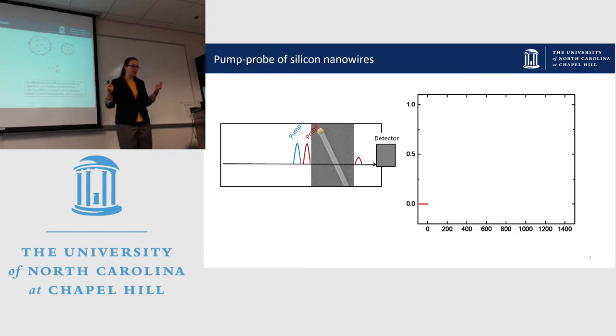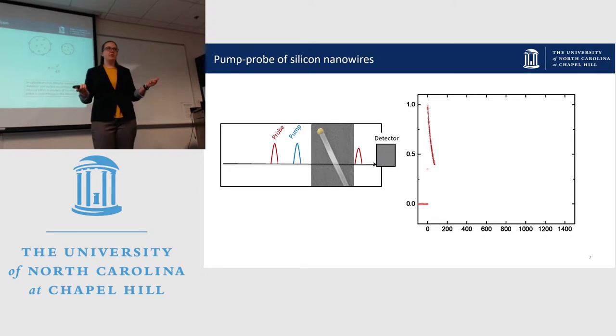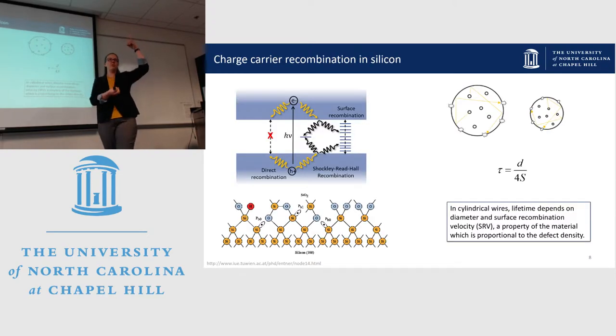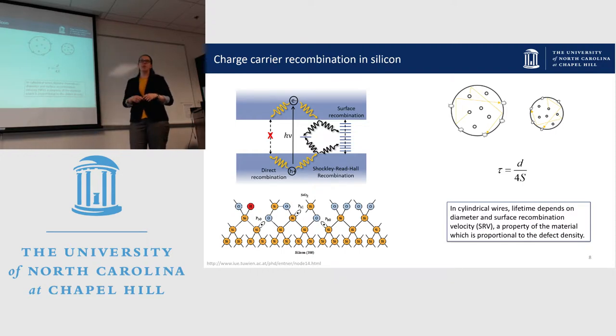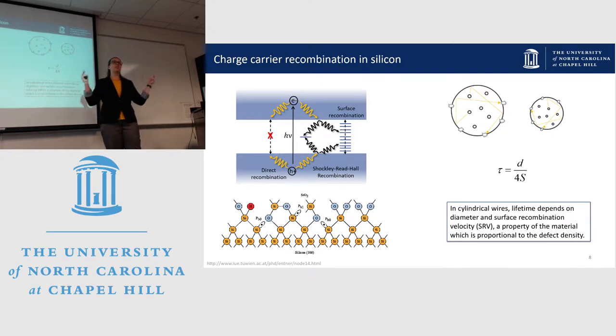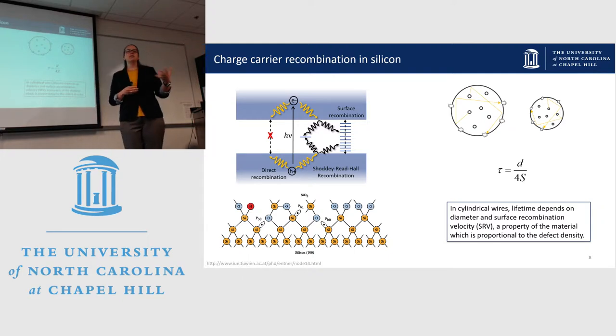So how does that recombination happen? Well, silicon is an indirect bandgap semiconductor, which means the electrons and holes can't just recombine with one another across the band gap. Instead, they have to go through some intermediate, what we call a trap state or recombination center. And these are usually defects like dangling bonds or atoms that are not silicon, so dopants or oxygen or hydrogen or gold atoms.